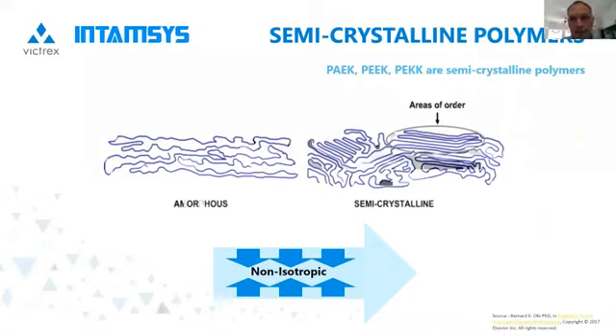And interspersed within the amorphous areas are areas of organized areas, the lamellar and spherulite areas. And these give the polymer this structure and rigidity. So typically the properties for amorphous polymers can be good impact resistance, but they can be more prone to things like stress cracking or poorer fatigue resistance. Amorphous versions are often transparent, or they have that translucent honey color.